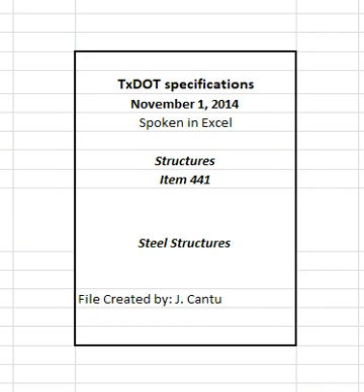Remove the zinc from the weld area of the test specimen and visually examine the surface. There must be no evidence of loss of weld metal or any deterioration of the base metal due to the galvanizing or welding procedure. Modify the galvanizing or welding procedure as required if there is evidence of deterioration or loss of weld metal, and run a satisfactory retest on the modified procedures before production work. Report procedures and results on the galvanized weldment worksheet provided by the department.